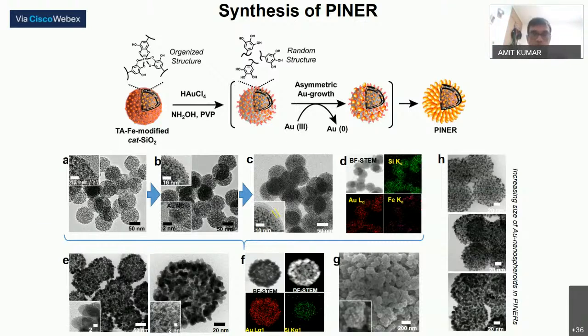The utility of this polymer is, number one, it is a structure-guiding agent. Without that, we cannot get such isolated branches around the nanoreactor. Another is that it protects the internal nanocrystals, because if the internal crystals grow into larger structures, they lose their catalytic activity. So developing this strategy is very crucial for getting this kind of final structure.